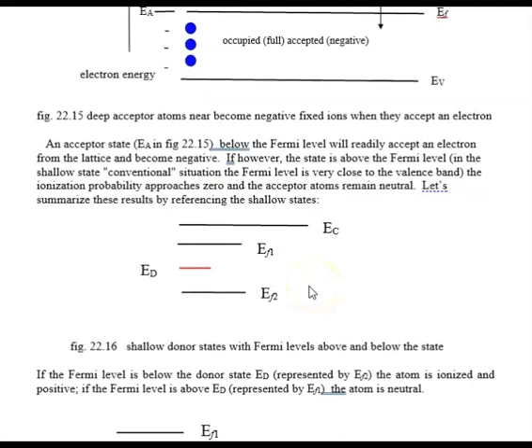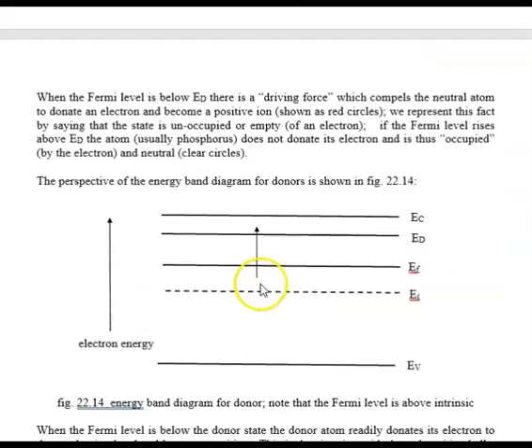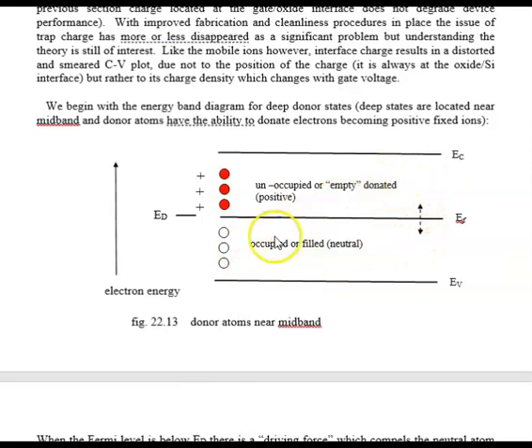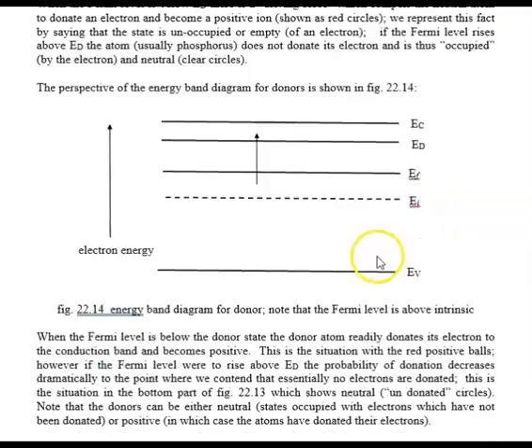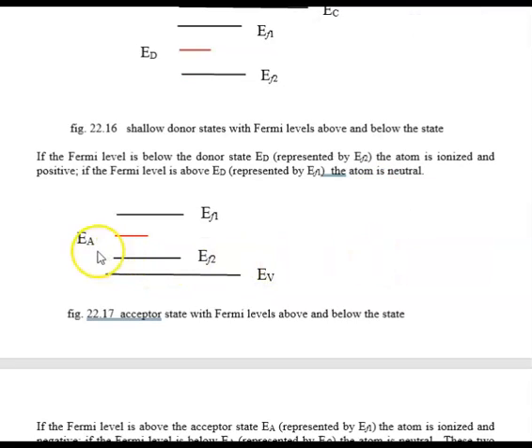And we can see in the summary of the energy band diagrams, let's first look at the donors. The donor state is indicated here in red. So if the Fermi level is below the donor state, that's the quote-unquote normal situation, then we have a donation. If the Fermi level is above the donor state, we do not have a donation, exactly as we're showing here. Fermi level high, no donation. Unfilled circles. Fermi level low, donation, red, positive ions.